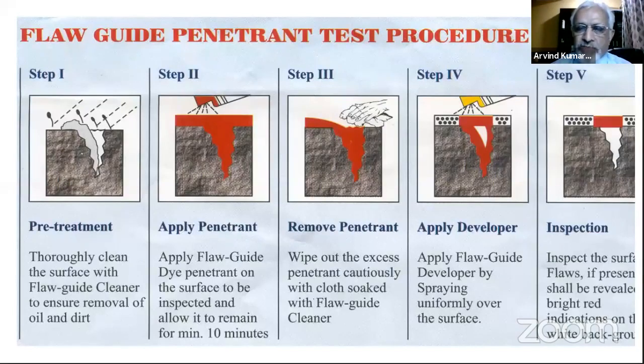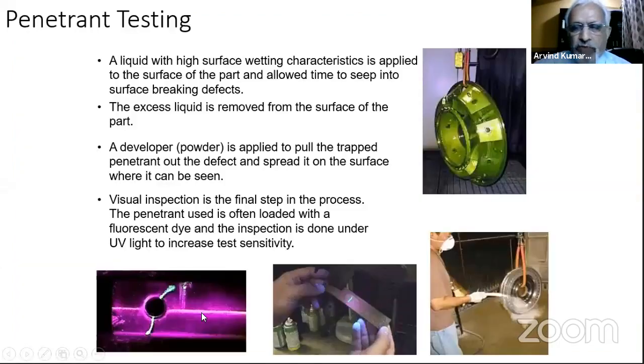Finally, once excess penetrant is removed, you have to apply the developer, which is a white powder mixed in an aqueous liquid. Once you apply it through an aerosol can, its volatile part gets evaporated, and what remains is the white powdery part. Once it is dry, we call the waiting period the developer dwell time. After about 10 minutes, the indication starts forming, and the penetrant which was inside the cavity will come out in the form of an indication which can be interpreted. So these are the basic 5 steps. Now we'll see in a subsequent slide what is important and what we tend to miss out in this.